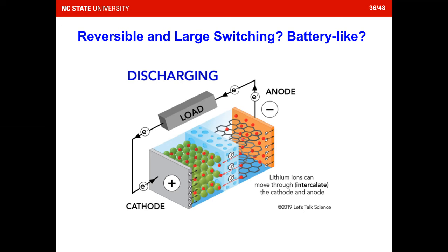is based on lithium ions intercalated or moving into the anodes or cathodes. That can completely change the structures of materials by creating disorder, right? As we mentioned, disorder is very important to create a lower thermal conductivity. So this is reversible and it could potentially have a large thermal switching ratio.